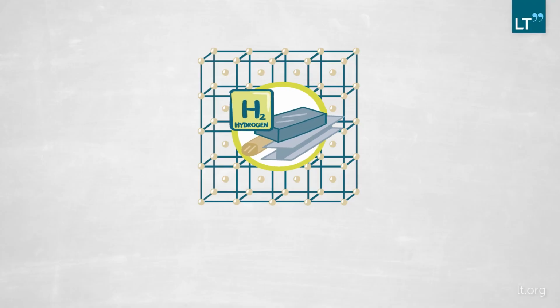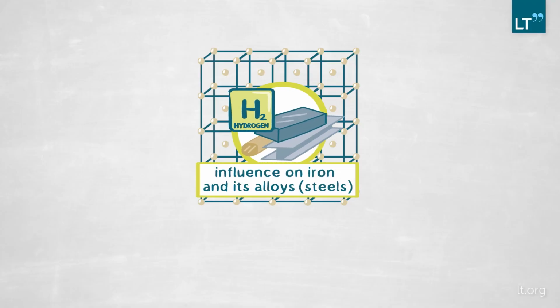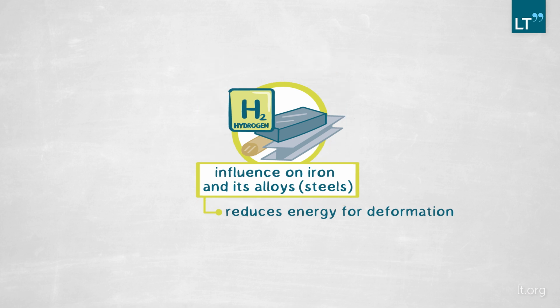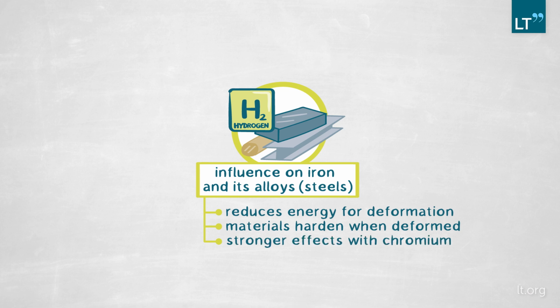Our findings can be divided into parts. First, let's consider the material per se. What we find is that hydrogen indeed has a very strong influence on the mechanical behavior of iron and iron alloys. This means, at first, it reduces the energy that is necessary to permanently deform the material. However, once the material is being deformed, it makes it harder. So this gives us a hint of an embrittling process. If we consider chromium, chromium makes this effect much stronger.